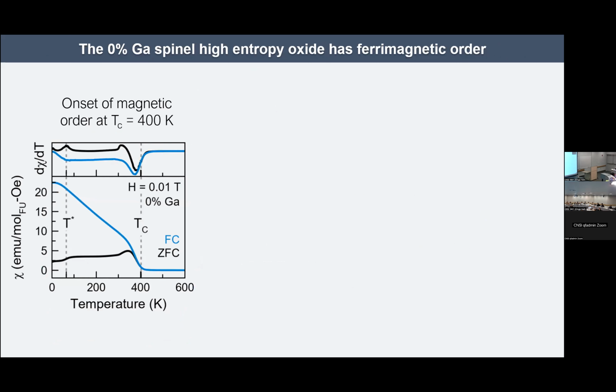Okay, so I'd like to begin with my characterization of the 0% gallium sample. This is our completely 100% spinel high entropy oxide. And what we found when we measured the susceptibility of this material, actually the first thing that we found was that we didn't understand what we were measuring, because we were measuring from room temperature to 0 Kelvin.